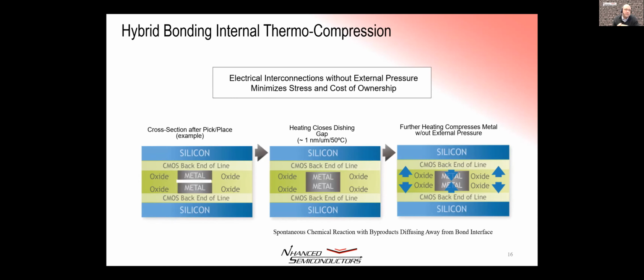How this works is after we've done that room temperature bond, it looks like the left-hand side. The metal we polish so it's recessed 30 to 50 angstroms from the surface. When we heat it up, we use nature, physics here. Metal expands more than the oxide. The oxide acts to pull this together. The metal extrudes, and it does grain growth across that boundary. So after we're done, typically this bond interface is stronger than the interfaces at the lower layers of metal on either wafer that's bonded.